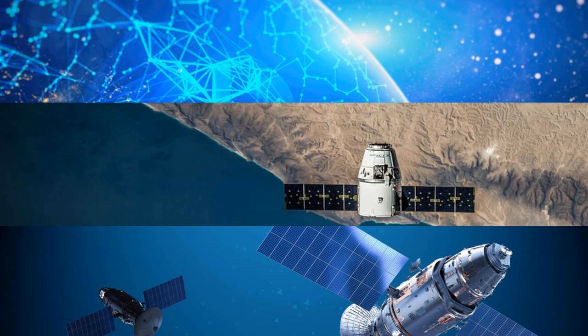So these pieces that we coated ended up sitting in storage for nearly 12 years, along with the witness pieces that were qualified with it. And when we tested it closer to the launch date, the results were incredible. There was no loss of adhesion, and the optical performance was basically unchanged. By the time the launch was already scheduled, we already knew that the coating could survive years of waiting here on Earth, which gave engineers a lot more confidence that it would stand up to the brutal conditions of deep space.